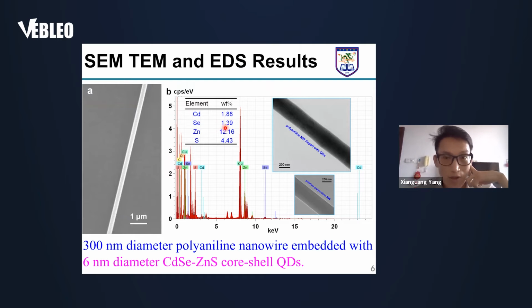Herein, we go to microscopic characterizations. Figure A shows the SEM image of a fabricated nanowire. And figure B shows the TEM image. This one contains quantum dots, and this is without quantum dots. The EDS results show that CdSe and ZnS were obtained from core-shell quantum dots. The diameter of the polymer nanowire is 300 nanometers, and the embedded quantum dots have a diameter of 6 nanometers.